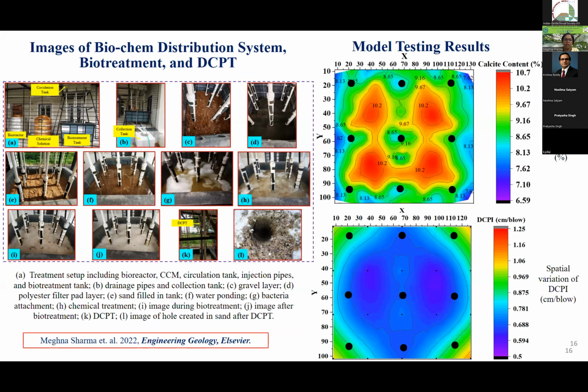After that, urea solution and calcium chloride dihydrate solution were provided to the soil for up to 7 days. Every day, biosparging was conducted for 10 to 12 hours, and the cementation solution was provided at every 12 hours of a 24-hour interval. This is the image in between the treatment, and this is after treatment. After the treatment, a dynamic cone penetration test was conducted at 20 different locations in the tank, and calcite precipitation at various locations was also determined. Our major aim was to achieve uniformity of calcite precipitation along the depth.